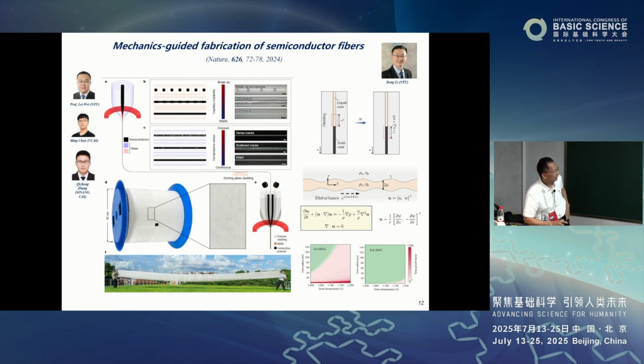So we thought of a way using optical fiber drawing under high temperature. You embed a semiconductor like silicon and germanium inside a glass cladding. Outside is glass. You melt both systems. So you have a semiconductor in fluid form embedded by the viscoelastic material shell. You draw it into wires. Here you have a molten stage, then you cool it down into solid.